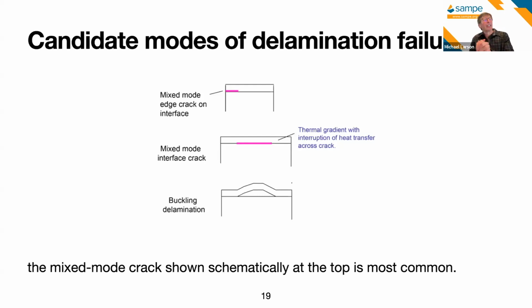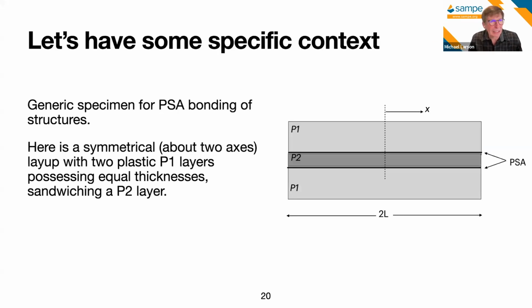So now, thinking about fracture mechanics being applied to candidate models of how delamination of adhesive surfaces with PSAs would look, we have edge delaminations proceeding from an edge. We can have an area between two surfaces bounded around a periphery that is separating. And we have buckling that is something of a distinct situation than that mixed mode interface crack. The buckling tends to be very much an opening mode sort of thing, whereas the mixed mode interface crack has a strong preference to shear, but there is some opening tendency. But it's the mixed mode crack at the top that is, I think, most representative of how typical failures occur proceeding from an edge.